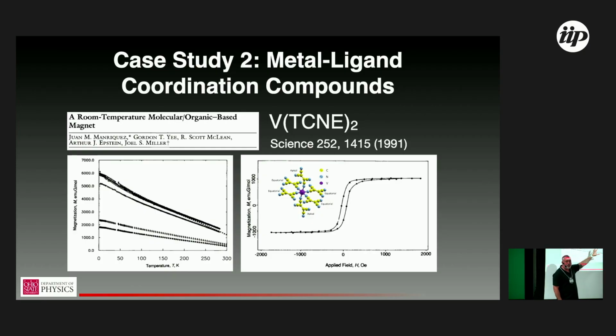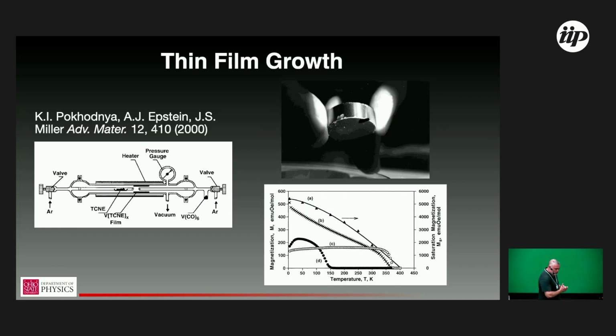This was pure solution chemistry, so synthesizing a powder, but you can see still showing very, very nice saturation, very clean hysteresis. Coming back to my earlier point, if we want to start off with ballparking the saturation magnetization, building off Michael's foreshadowing, and we've now changed units, so this is Oersted. So the saturation magnetization was out here for the Prussian blue. It is significantly lower field for this VTCNE. So this was the initial discovery. Joel Miller, a chemist at the University of Utah, and Art Epstein, a physicist at Ohio State, which is how I came to find out about this material.